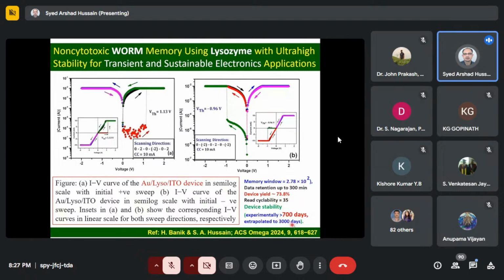Then device stability, it's very interesting. You know, normally biomaterials are less stable, but here we have found that our system is stable. We incorporated clay, natural clay, in between the device, and we found that the stability of our device physically, that means experimentally, is more than 700 days. Then we extrapolate up to 3,000 days. Still, the memory window was good with respect to practical applications.